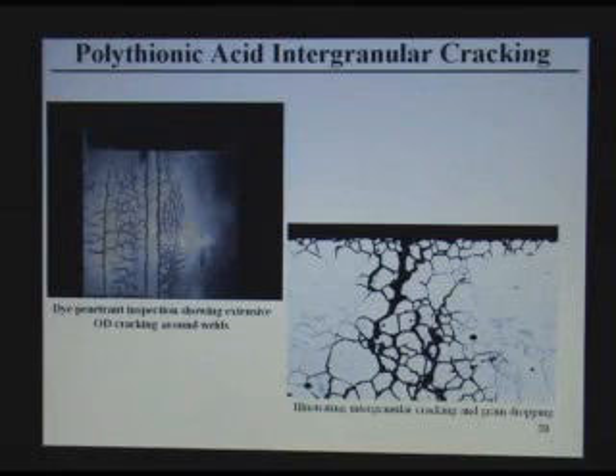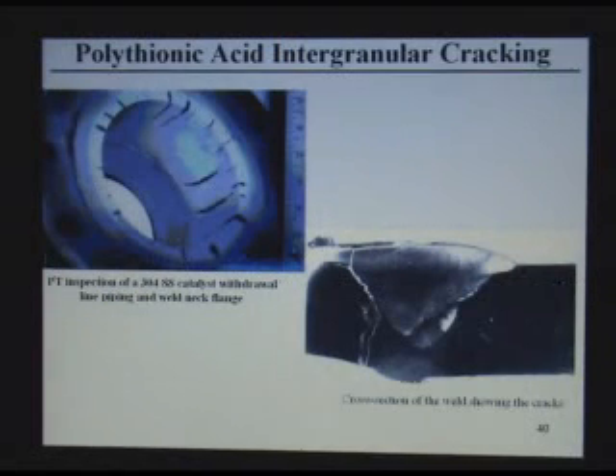Polythionic acid cracking is a phenomenon where stainless steel, which is made of alloy, has some carbon, and carbon diffuses into the grain boundaries and forms chromium carbides. And if you have areas rich in chromium carbides and adjacent areas less in chromium, you have a galvanic cell here. And if the conditions are wet during shutdown time, corrosion occurs at the grain boundaries. And in case of thermal stress, there is no bond anymore, so it cracks around the grain boundaries. This is another example of polythionic.